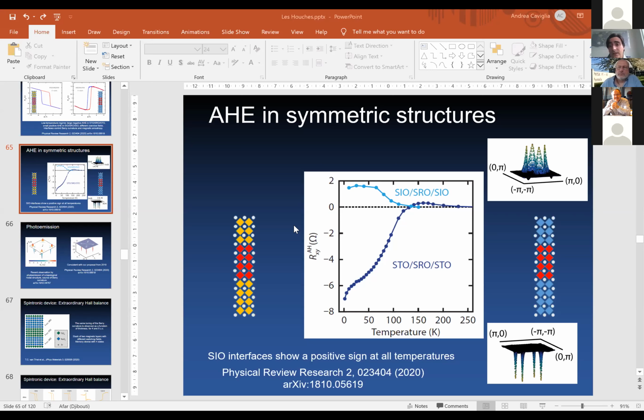Yeah, that's a very good question. So when you have thickness inhomogeneities, what I think is happening is that you have both contributions. You have both a positive contribution to the anomalous Hall effect and a negative contribution. And these are spatially inhomogeneously distributed in your sample. So probably you will have a pattern along step edges in which you have maybe a larger thickness and a smaller thickness next. So this creates a situation in which this extraordinary Hall balance behavior is observed in a single inhomogeneous film.